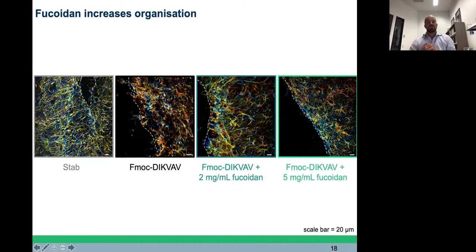Okay, so then what we did is we actually functionalized this hydrogel with a molecule known as fucoidan, basically, again, to present that galactose moiety. And what you can see here, these are pictures of the brain. So this is a lesion, the black here is a lesion. These are all at the same magnification, but this is a stab injury, and you can see this fibrous-like growth of these astrocytes here. And it's really messy and disorganized. Once we have this hydrogel presented into the void, so the hydrogel is where the black is here, you can see that there's much less reactivity.